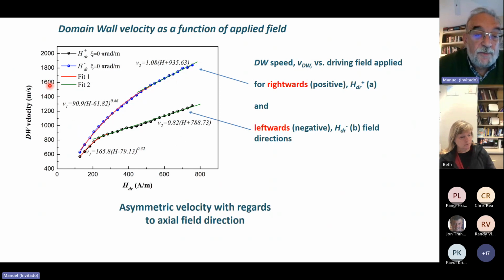We have the velocity of the domain wall as a function of the driving field. In this case, we do not have any local field coil, but you see there is a linear behavior after the transient behavior, we have a linear behavior of the velocity with the applied field, but we observe two slopes. When we apply the field to the left or to the right, so a negative or positive field, we see that this linear behavior has a different slope. And we wanted to know which is the origin for this asymmetry in the velocity with regards to the direction of the applied field.